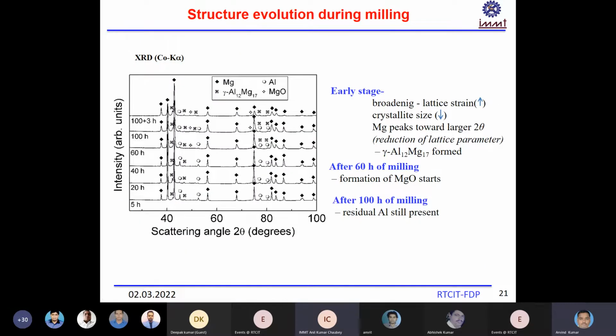So what we have done to extend the solid solubility of the aluminium in magnesium, so that you can reduce the gamma phase formation: the mechanical alloying was done for 5 hours, 20 or 40. We have gone to 100 hours, and we see that there is still a small gamma phase here, and then it was again done for 3 hours of cryomilling to make the particle size very small.